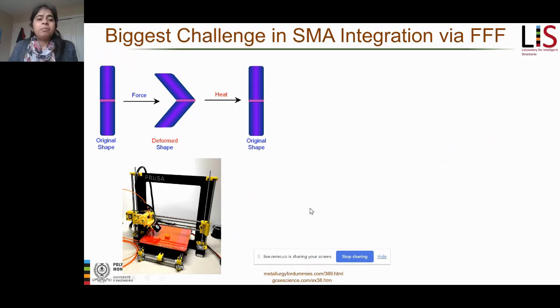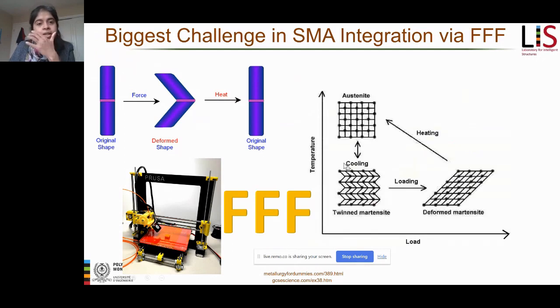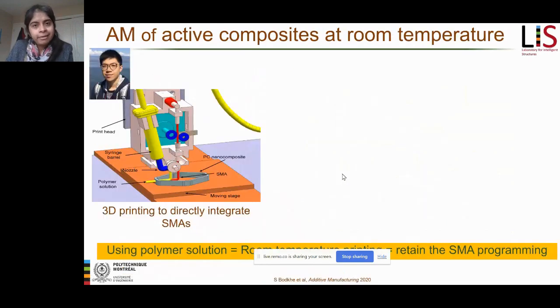The problem with going all FFF was that if you go above the transition temperature of the SMA while you are integrating the SMA in the structure, you're going to deform it. And we didn't want to do that. So we tried to develop a direct ink write method where we would deposit these shape memory alloys between structural material that was dissolved in a polymer, dissolved in a solvent, which would evaporate after extrusion. In this way, we could print these structures at room temperature.